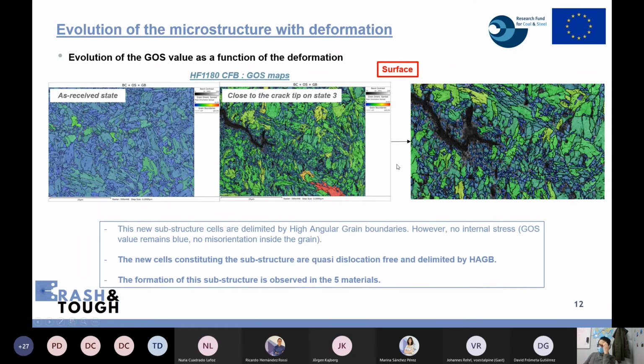Now with the GOS maps, we can see the evolution of the deformation. This is again the HF1180 CFB, far from the crack and close to the crack, at the state 0 and the state 3. What we can see when we zoom on the state 3 is the presence of this substructure, and that these dislocation cells are dislocation free, and that they are separated by high angle grain boundaries. Inside the cells, there is no dislocation, no misorientation. And this is also observed in the 5 materials.